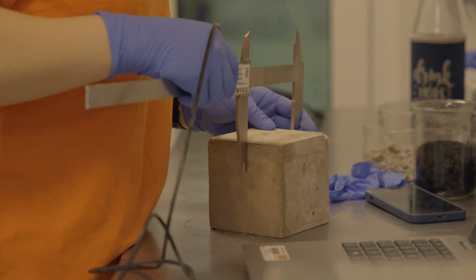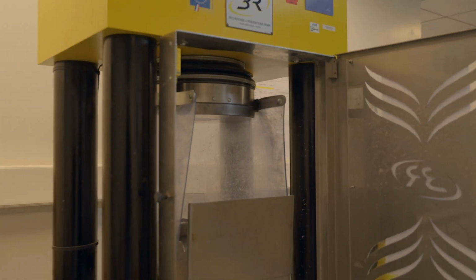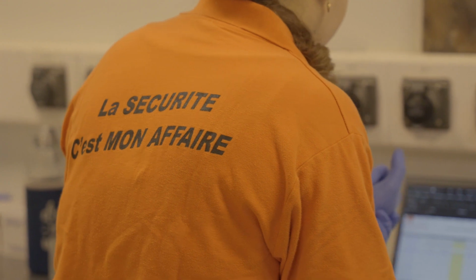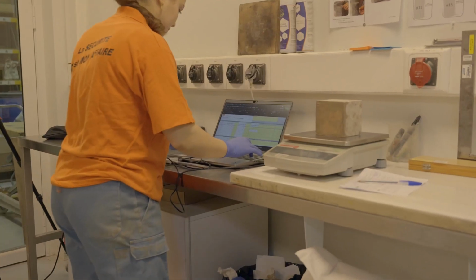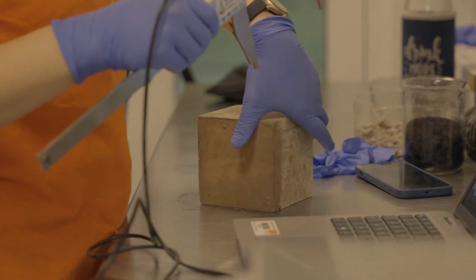Mechanical tests such as compressive strength or bending allow us to verify that the formulation meets the specifications. Several factors influence mechanical strength, whether it's the cement, its type, the quantity, the aggregates, or the amount of water. And here I would like to point out that the more water you add to the mix, the lower the mechanical strength becomes. So, you should never add extra water to the concrete mix just to improve its workability, because this will harm the mechanical strength later on, and you won't be able to meet the specifications.